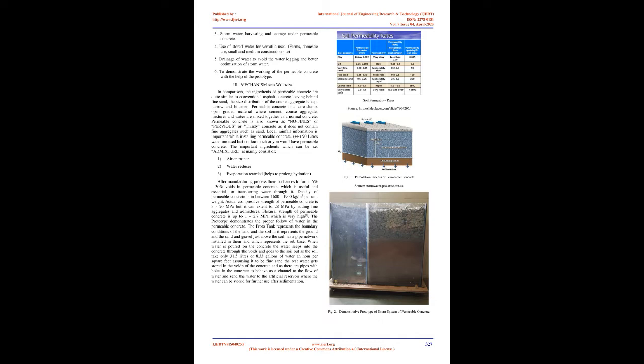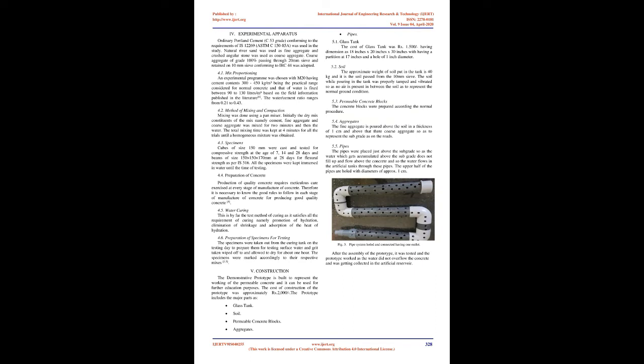Local rainfall information is important while installing permeable concrete. About 90 liters of water are used, but not too much or you won't have permeable concrete. The important ingredients are admixtures, which mainly consist of 1. Air entrainer, 2. Water reducer, 3. Evaporation retarder, which helps to prolong hydration.